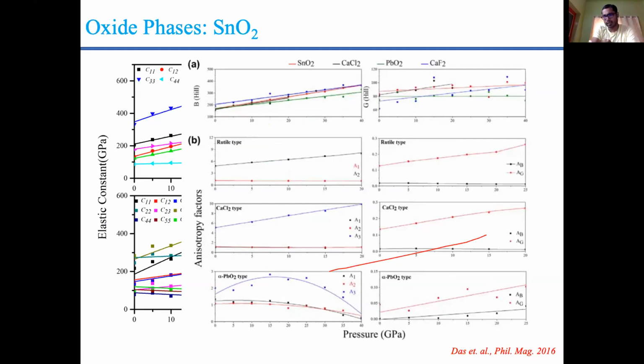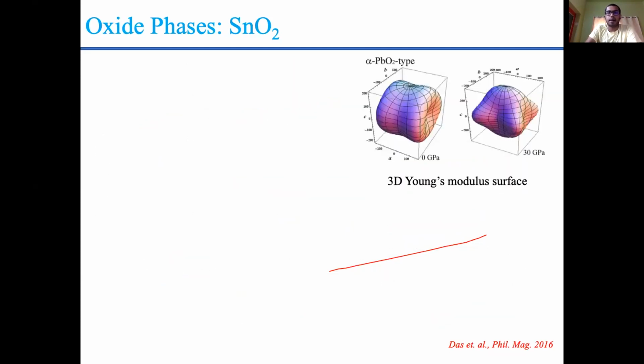So I have calculated the two directional anisotropies, that is A1 and A2, whereas CaCl2 and alpha PbO2 are orthorhombic, so I have to calculate three different directional anisotropies. The significant part of this plot is the alpha PbO2 case, where you can see a strikingly different nature, and almost all this anisotropy shows a reversal at around 18 GPa, which suggests a more typical crystal mechanical behavior of this phase. Thus, we examine the Young modulus surface at ambient and high pressure.